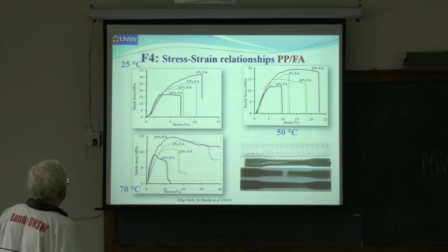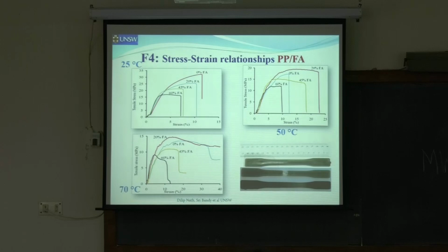So, stress-strain relationships of polypropylene fly ash. The top one is 0% fly ash, and 20% fly ash here. Please take note of the y-axis, which tells you the limit. They all look like the same height, but here it is about 33 MPa, here it has come down to about 17 MPa, and here it is about 12 or 13. Although the graphs look the same height, the scale makes the change.